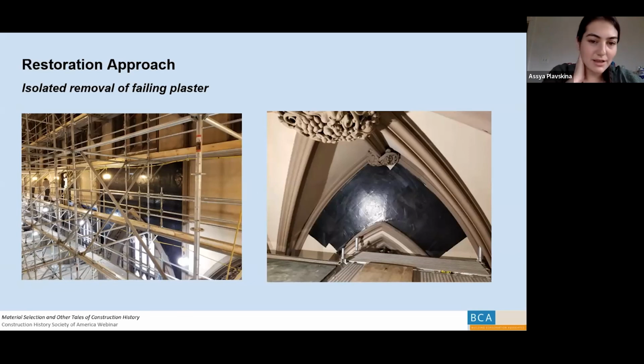After much testing that we don't have time to get into right now, we found that the most efficient and safest way to get our failing layers off of the wall was to use duct tape. So what you see there in the black is actually large rolls of duct tape, and we went through multiple different types of adhesives to really identify the best one. Large rolls of duct tape were applied to all of the plaster surfaces of the wall, and when they were removed, only what was failing came off the wall, and what was well bonded, well adhered, remained on the wall.